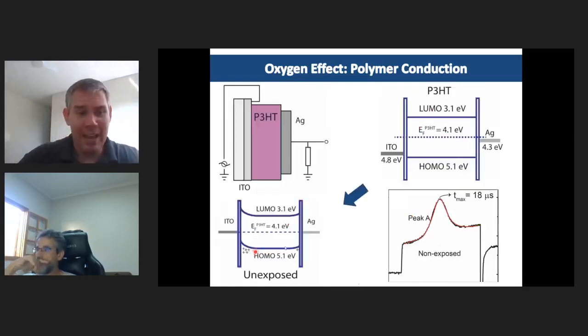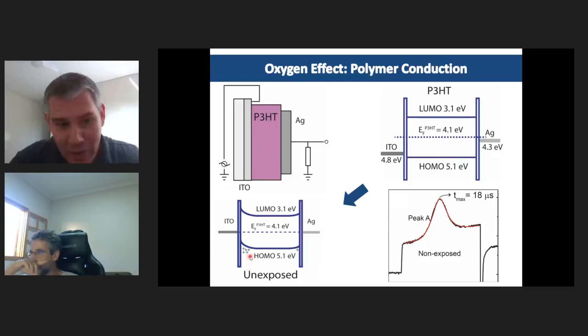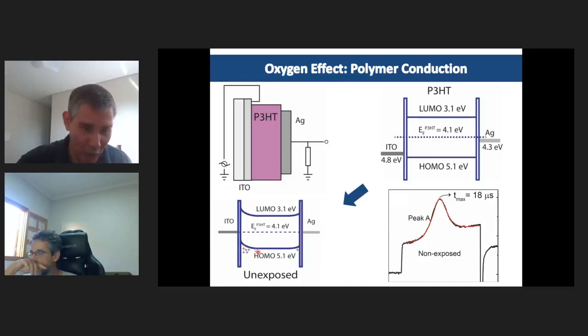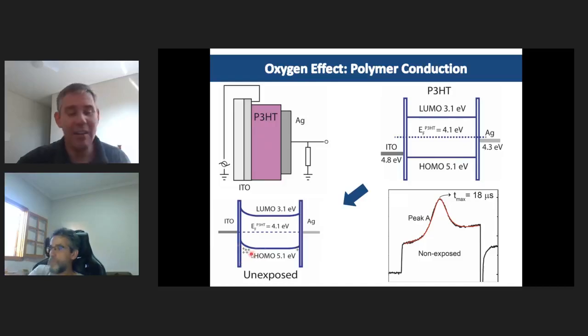And then we sort of understood the nature of the Peak A which is related to the non-exposed device. That extraction of charges is basically extracting those charges that are actually at the interface between the ITO and P3HT, to sort of work out the energy break at that interface.